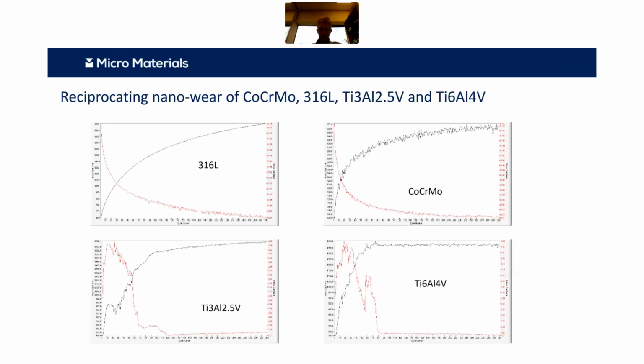More recently, we haven't published this yet, but we've been looking at small-scale reciprocating wear tests. And now we have designed these reciprocating wear tests so we can look at friction and depth, cycle by cycle, quantitatively, all corrected for any thermal drift that might be happening. And there you can see just an example of, sorry, it hasn't come out that well, how the friction changes as it polishes out on the 316 and the cobalt chrome, and it's initially very high on the titanium 6-4 and also on the titanium grade 9 that you see on the left, and that's accompanied with more wear until eventually removing that.